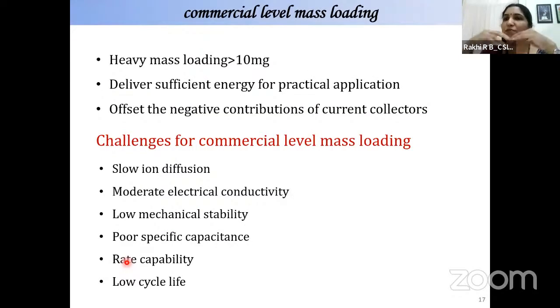Then we went for fabricating symmetric supercapacitors with the MoS2 nanostructures directly grown over the nickel foam substrate. But there we encountered another problem. In lab scale testing, we used to test with less than 4 milligram of the active material. From the previous study, I have done testing with 1 milligram of the active material. But here we found that each electrode had a mass loading of more than 30 milligram. So what is meant by 30 milligram? Anything above 10 milligram can be considered a commercial level, industrial or commercial level supercapacitor.